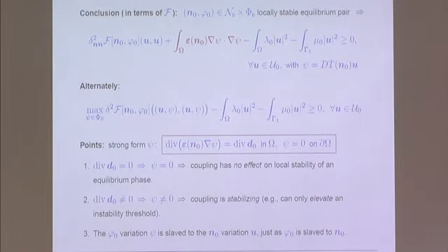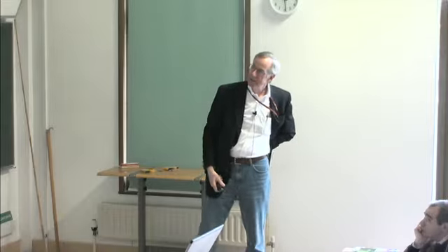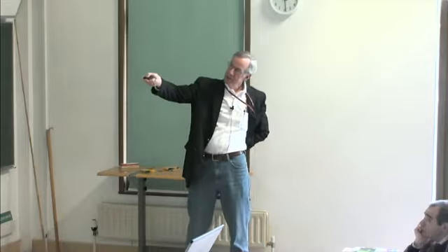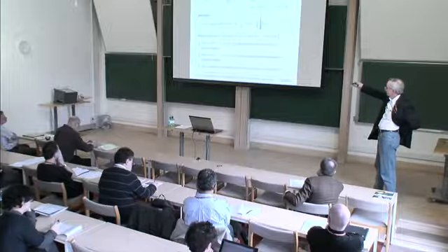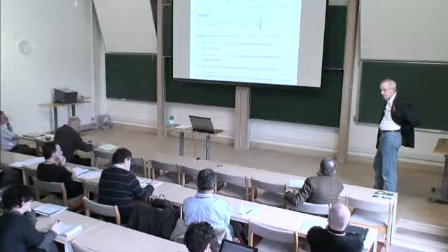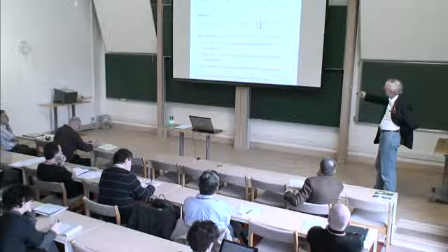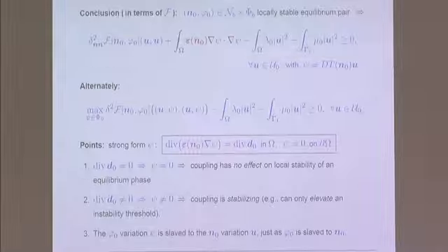This is the relationship between a perturbation u in the director field and the perturbation psi in the electric potential. It satisfies an electrostatic problem, but it now has something playing the role of a charge density on the right-hand side. D naught has the same units as a displacement or a polarization. So this is some kind of effective charge density, and this is like an anisotropic Poisson equation with homogeneous boundary conditions.